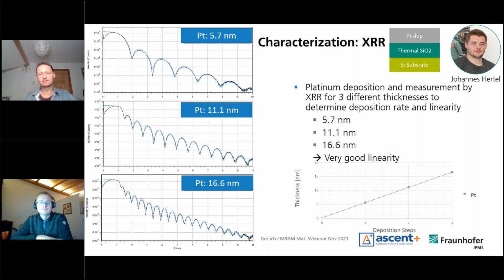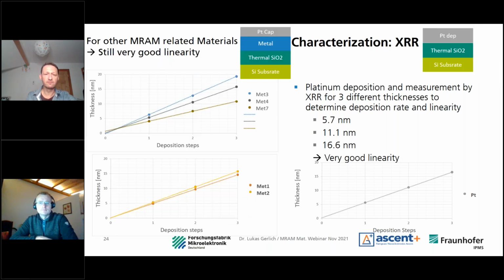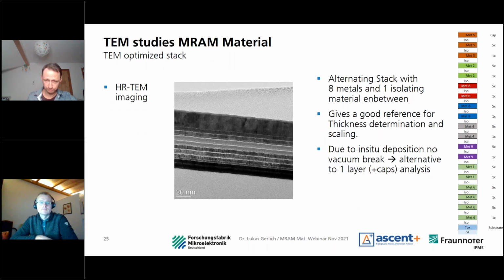And here's an example of a platinum deposition of 3 different thicknesses to see if the linearity is very good, and therefore we extrapolate even to lower thicknesses to have nominal values. And this is also true for nearly every material we used. That is quite usable, and you can work with the extrapolation.